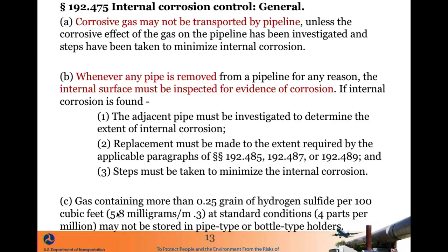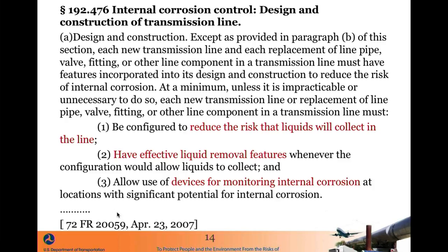So in the natural gas code, it pretty much says, corrosive gas may not be transported by pipeline. So it's pretty clear, prescriptive on that. And it says, whenever a pipe is removed from the system, the internal surface must be inspected for evidence of corrosion. So whenever you're doing pipe replacement, that's something that you need to be looking for. And since the 2000 Carlsbad incident, this regulation was put into Part 192.